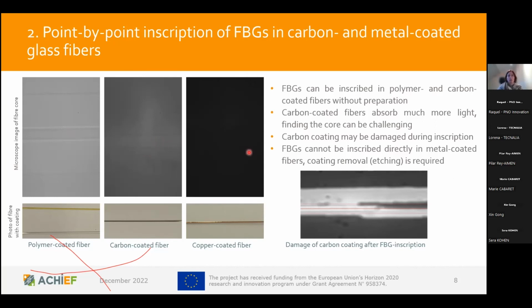However, for the metal coating, of course, the detection algorithm does not work anymore. So we actually settled for the bare or the carbon-coated fibers for the fiber Bragg grating inscription step. Some parameters needed to be tuned. As you see here, the carbon coating can also get damaged during the femtosecond laser shot procedure. However, we managed to find a nice set of parameters that actually works for our purpose.